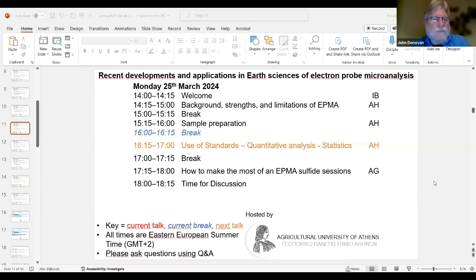I'll just mention during the break that I don't know if you've had a chance to try it out, Annette, but there's a new feature that I added a few months ago in the software where if you have at least 3 points in a sample and they're not in a line, then it will use the Z positions of those points to calculate a sample tilt, and then it will apply an effective takeoff angle to all your analyses. I tested it out by putting a sample into the instrument, tilted as much as I could, and it worked. Absolutely, and that will be so useful for that.